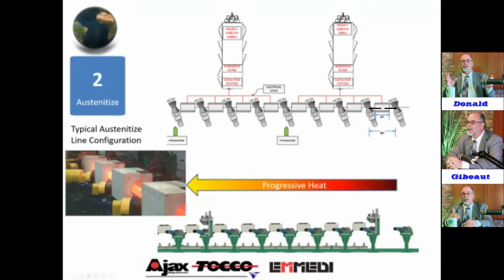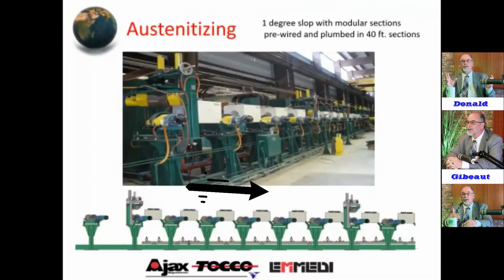Here, a typical coil is 28 inches, and the distance between the centers of the rolls is pretty standard at around 60 inches. Most of our austenitizing lines are built on a 1 degree slope, so that any quench water on our very aggressive quench, if there are any gaps and it gets put into the inside, because it's not a perfect seal by any means, and we're really throwing the coals to it on pressure somewhere. We have lines running at 7 to 10 psi on the individual circuits on the quench, going up to 35 to 40. So the 1 degree sloping helps us keep water from going back up into the coils.